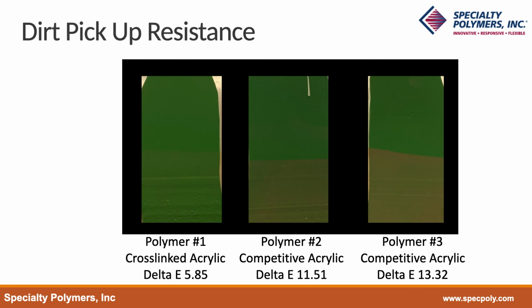These are the panels from the dirt pickup resistance test. The cross-linked acrylic had better dirt pickup resistance than the competitive polymers. So even though it had better flexibility in the low temperature flex test, it didn't pick up as much dirt. Again, this may be due to the cross-linking in the polymer.